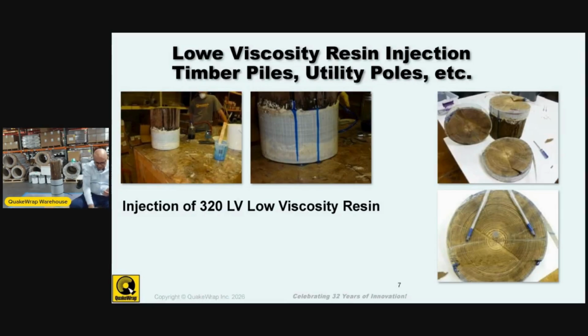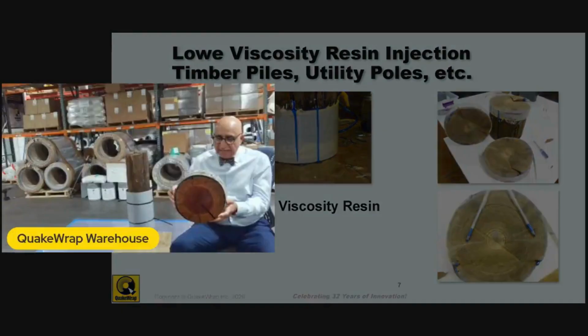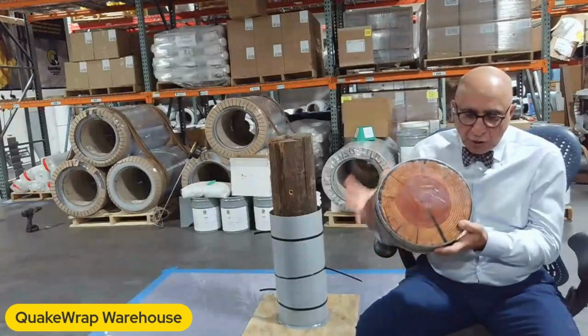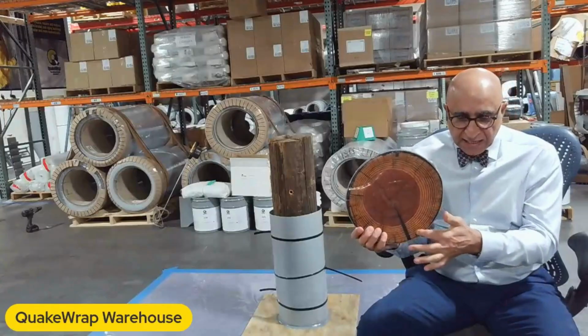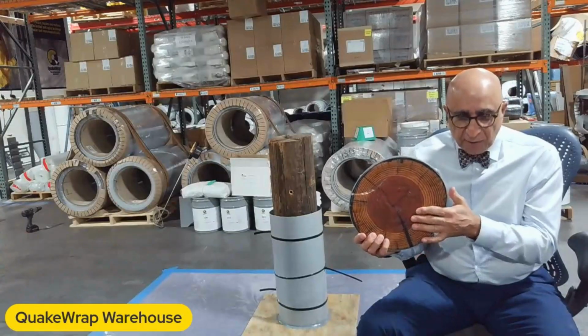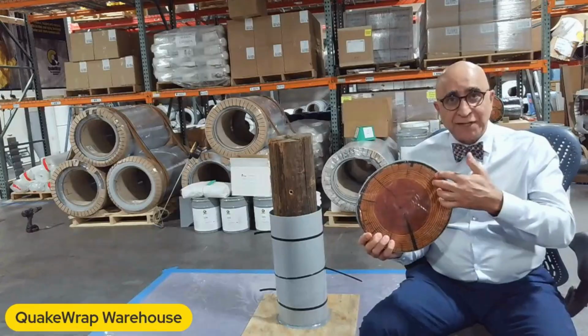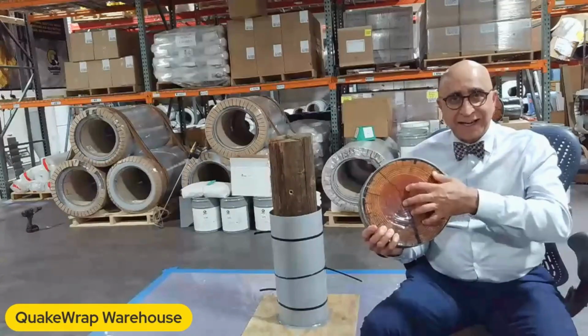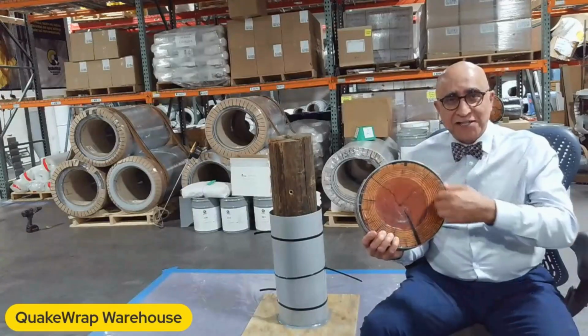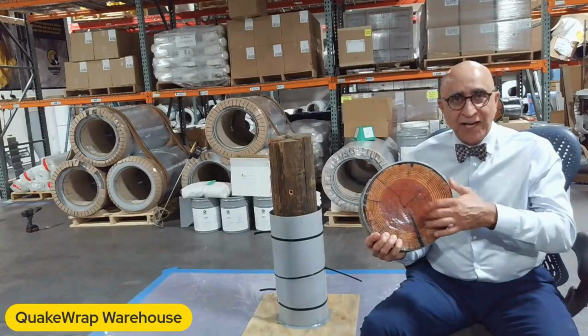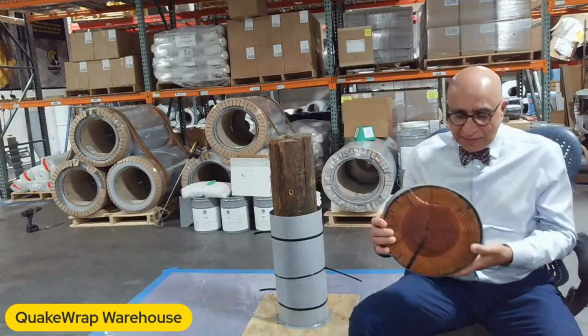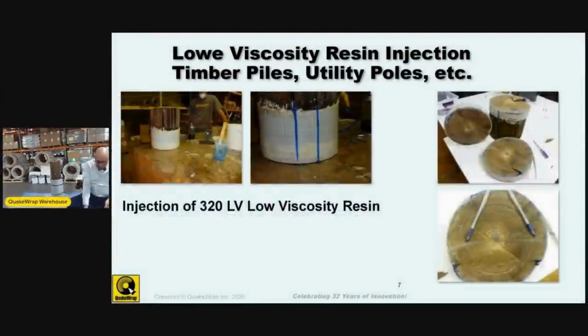As you can see, and in fact, I can hold one of these up for you, this is how the resin finds its way into all these voids and cracks that normally are not visible from outside. When you fill it with resin, the resin kind of magically finds all these cavities inside of the pile and fills them up. That's really the concept of how you would use it to add to the strength of your repaired pile.